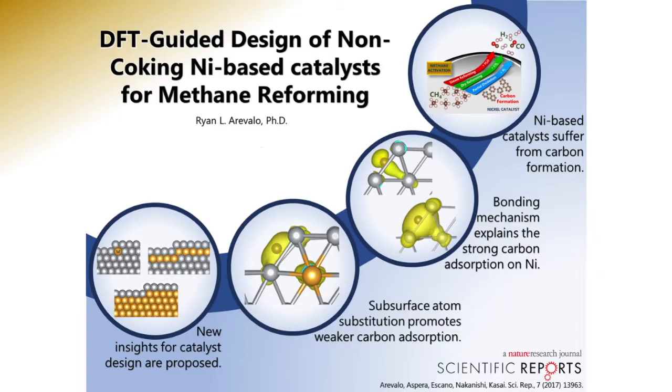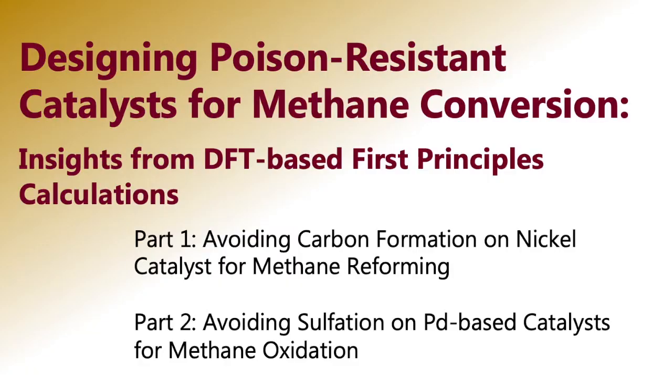I have also shown that substituting the subsurface atom with another element can promote the weaker adsorption of atomic carbon, thereby changing the reaction mechanism of methane decomposition happening on the surface. And from such results, we propose some new models for the catalysis of methane decomposition with the use of nickel-based catalysts. This presentation is the second part where I will be talking about sulfur formation or sulfation on palladium-based catalysts